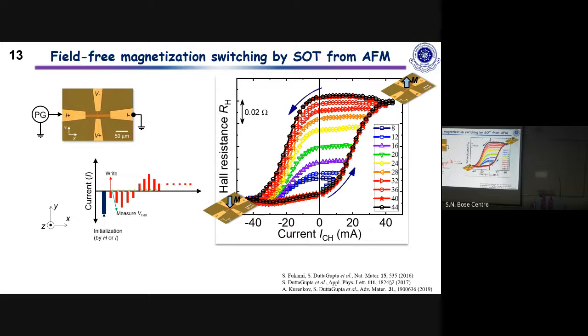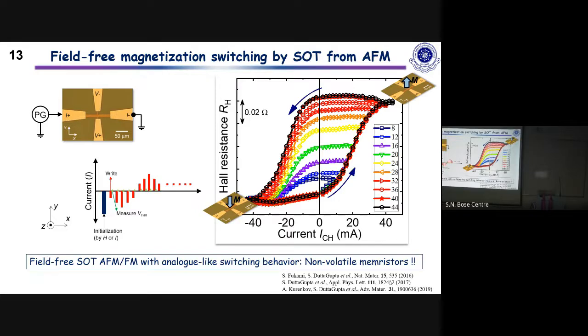More interestingly, we see two things. First, without an applied magnetic field, we can switch the magnetization. So the requirement of the external magnetic field has been eliminated. And secondly, we also see that there are multiple resistive states that can be stabilized here, which is generally not seen in other ferromagnetic bilayer systems. So this led us to propose that with an antiferromagnet-ferromagnet system, you can have field-free switching, and that too with an analog kind of switching behavior. This indicates that we can use a spintronic bilayer system to make non-volatile memory or devices which have multiple resistive states.